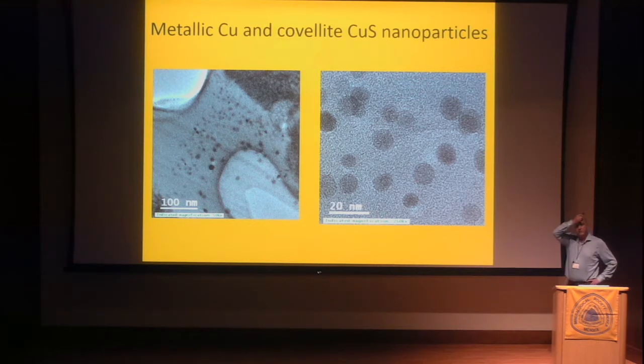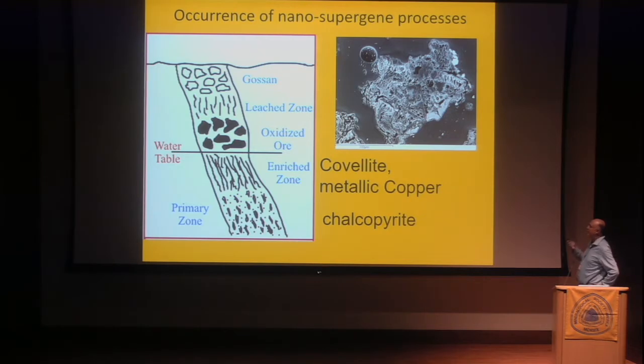Now, when you work in the environmental science field, you sometimes don't recognize right away analogies to larger scales. And it took me a while to understand that we actually look here at a nano-supergene process. In a supergene ore deposit, we normally have the primary minerals, the chalcopyrite, and then the chalcopyrite in the oxidized zone is oxidized and leached, and some of the copper and sulfur is leached back to below the water table, where we have an enriched zone in covellite and metallic copper. And exactly the same procedure we see here.